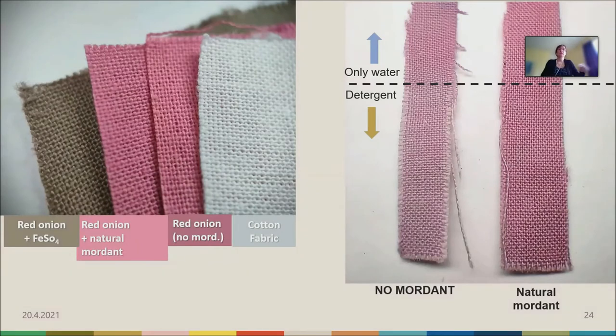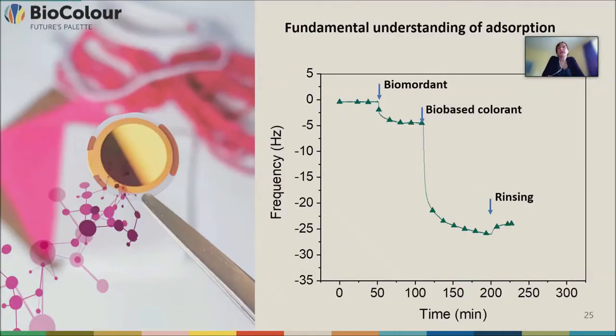And this is an example of how these dyed fabrics look. So if we take the white cotton fabric and use the red onion extract, we get a nice pink color. But this pink color does not withstand washing. So clearly it changes color and becomes lighter with the washing, especially if we are using detergent. So we need a mordant, as said. If we use the commonly used iron-containing mordant, it gets brown. So this is not very nice, if we wanted to have the pink color and we get the brown color instead. So with the natural mordant we tested, we could actually retain this nice color, and it could also withstand washing rather well. And what we wanted to do was understand this a bit better.